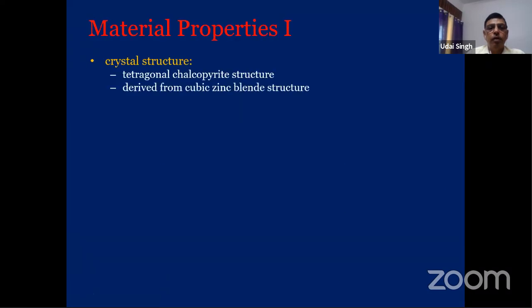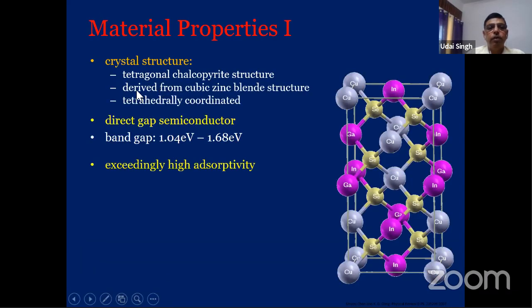As I said, the crystal structure is tetragonal chalcopyrite structure, which is derived from the cubic zinc blende structure, which is tetrahedrally coordinated. It's a direct band gap semiconductor. The band gap you can vary from 1.04 to 1.68 electron volt by replacing indium by gallium. Copper gallium selenide is around 1.68, and copper indium selenide is 1.04. The absorption coefficient is exceedingly high for this material, so you can absorb most of the spectrum within 1 micron thickness.